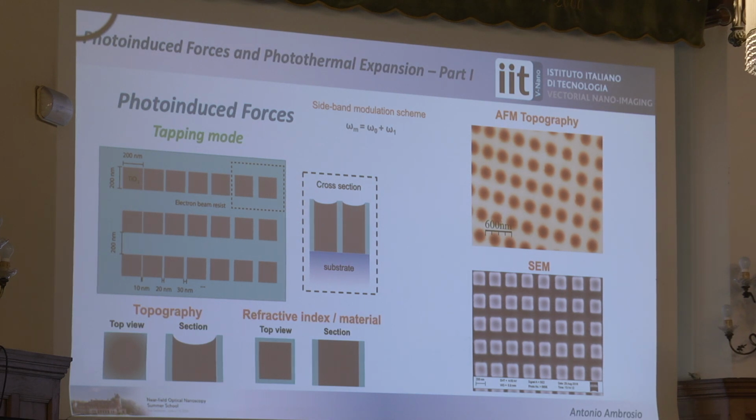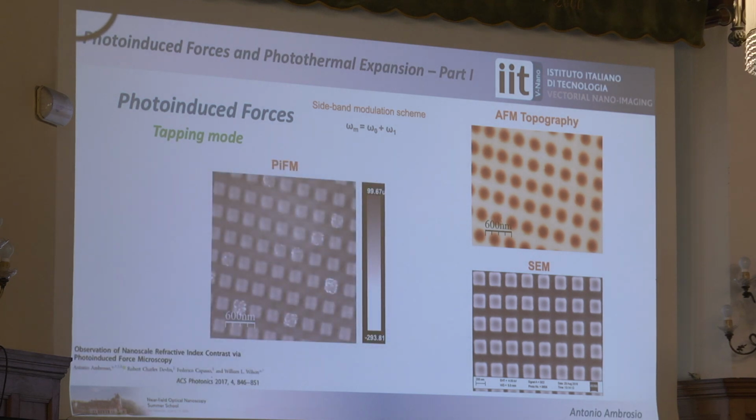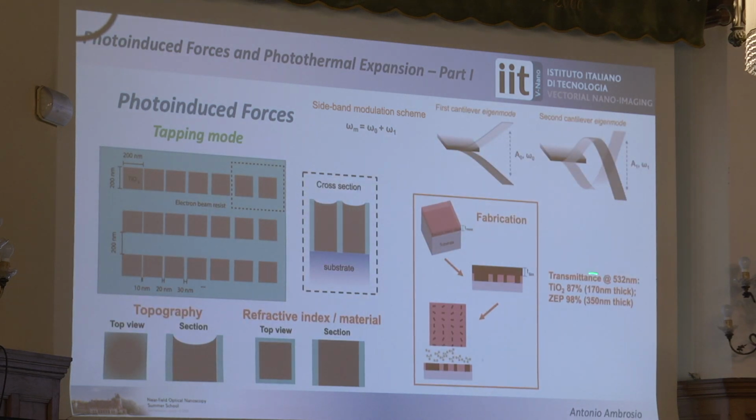Now, when you do tapping mode for the induced force, or tapping mode mechanical detection, let me call it like this, without saying if it's thermal or optical, you get squares. That to me means that you are sensitive to the refractive index. Also because titanium dioxide, and I think I have this number here, if you look at the transmittance of titanium dioxide and ZEP at the excitation wavelength, they are almost transparent, both of them.